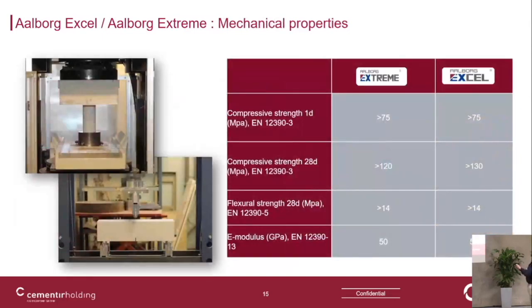Then the mechanical properties. Of course, the strength, the compressive strength. We have, at one day, we reached already a level of more than 75 MPa. We even had results of around 100 MPa. So these mixes are very reactive, and there is a high cement content in it. So that makes that you have the strength development mostly in the beginning of the hydration.